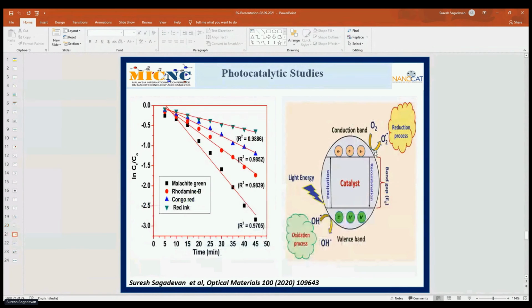And next, from this figure, we plot the graph between time versus ln(C/C0), the kinetic studies. From these kinetic studies, we calculated the R squared value. That means the rate constants were calculated based on the slopes for each dye.